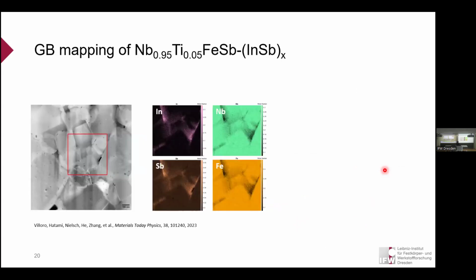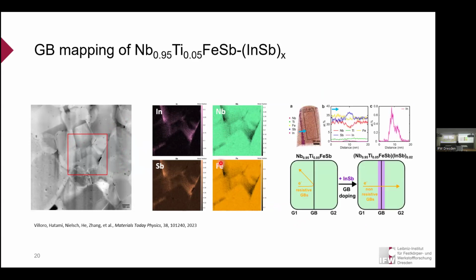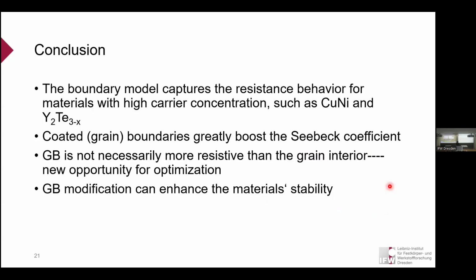Then we do characterization, and the grain boundary mapping tells us that there is indeed an enrichment of indium and antimony, which corresponds to a depletion of niobium and iron. So basically, this is indium antimony there. Following atom probe tomography, we also see an enrichment of indium across the boundary. That means we can effectively change the grain boundaries from resistive to non-resistive grain boundaries to increase the performance. Okay, so to make a conclusion, we can use this grain boundary.